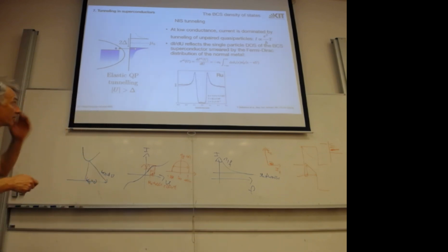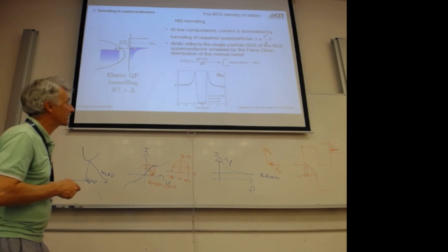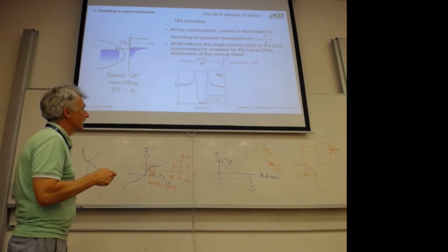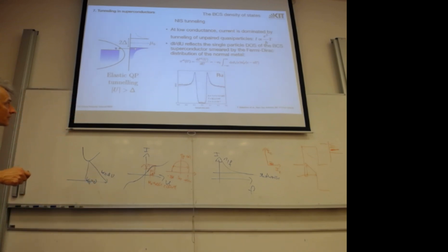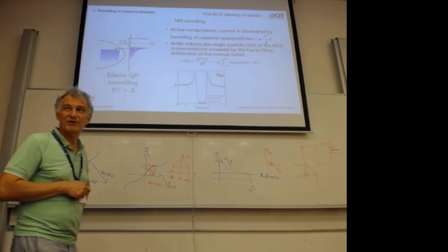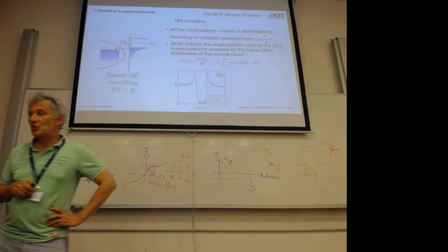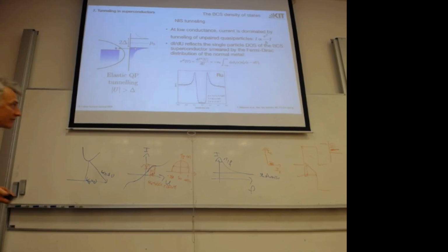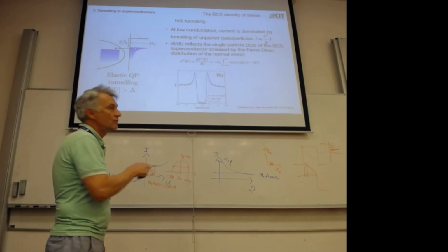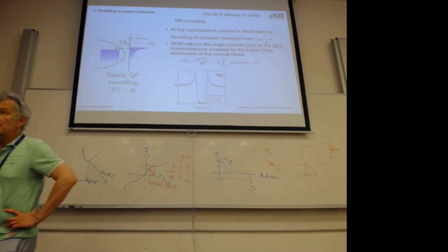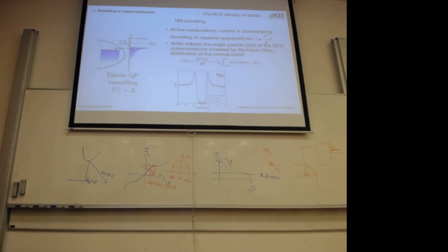So it's a simple convolution of this Fermi-Dirac function and our superconducting density of states. And that means from this you can get the deviation from the ideal BCS. And that gives you an idea of how good your temperature actually is. So our system works at 25 millikelvin. If you fit this, you need a temperature of 82 millikelvin. And this is the so-called electronic temperature.